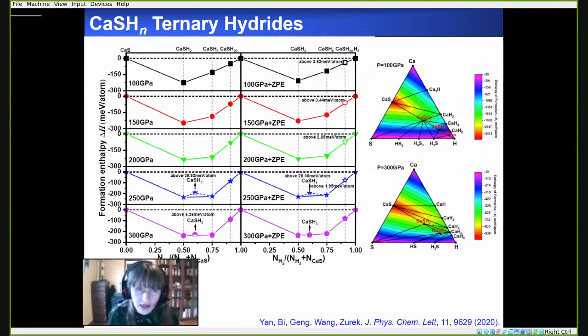So other ternary hydrides that we have considered are those containing calcium, sulfur, and hydrogen. And here I show what is called a convex hull. If you plot the enthalpies of formation of your species on these types of 3D convex hulls, you can figure out which species are going to be thermodynamically stable. Those are the ones that lie on the convex hull, and those that are slightly above the convex hull can be metastable, provided that their phonons are all real. So that means that they are kinetically stable.